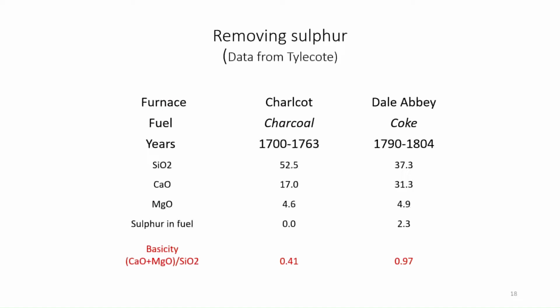These figures here are from a gentleman called Tylecote, and you see that in the 18th century, the charcoal furnace at Charlecote ran a basicity of slag of 0.4, whereas Dale Abbey, which was on coke, ran a basicity nearer 1. The basicity, as you'll see here, is calcium plus magnesium over silica.